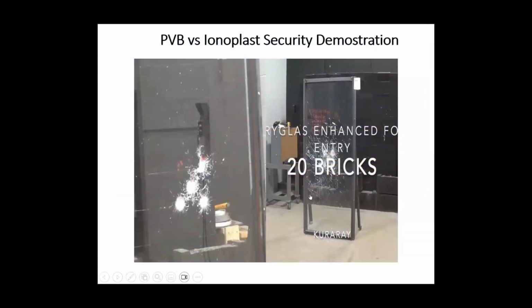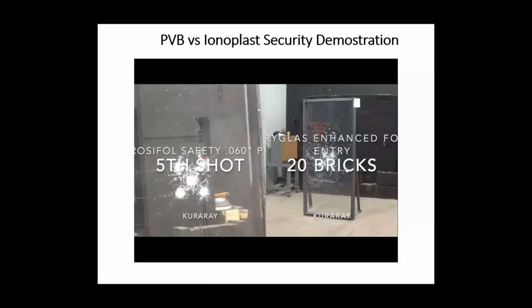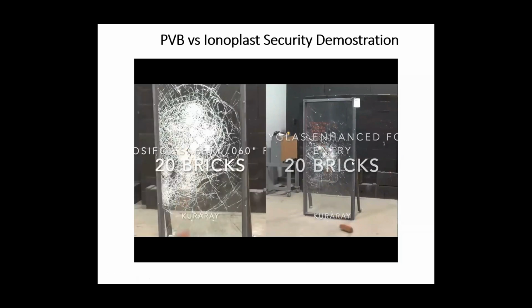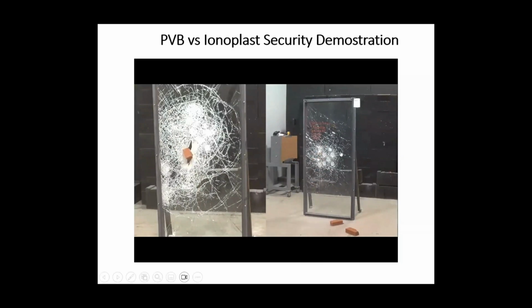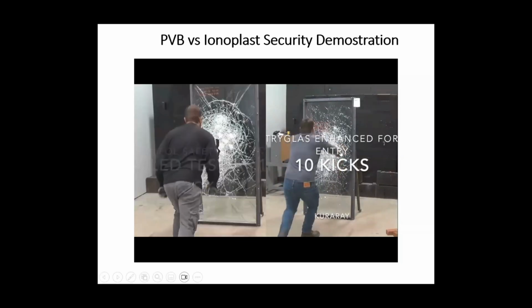Okay, so here's a test that we performed. In this test, the glass was shot 5 times with an AK-47. And then many different tools were used to try to break through. On the left will be PVB, and on the right will be the ionoplast. Yeah, on the left, the PVB is already torn.